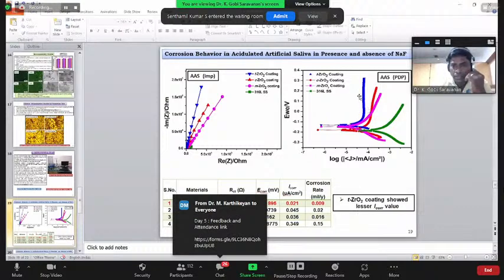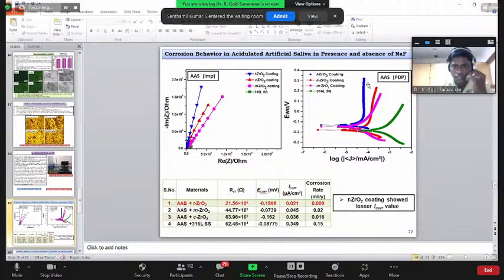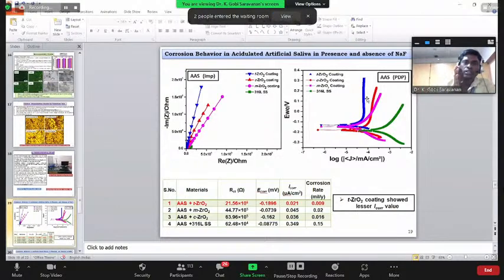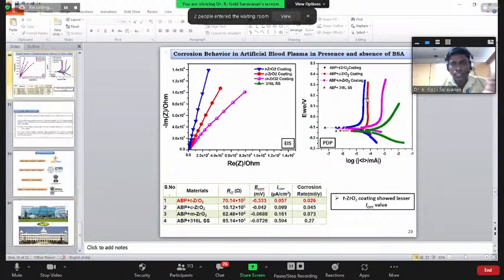But here in particular, of all three materials, which one is best? This is the tetragonal. Tetragonal zirconia shows more corrosion resistance than cubic as well as monoclinic. So from this observation, we can conclude that the tetragonal zirconia coating protects against corrosion better than the monoclinic as well as cubic. Then we did the same with the artificial blood plasma with bovine serum albumin.